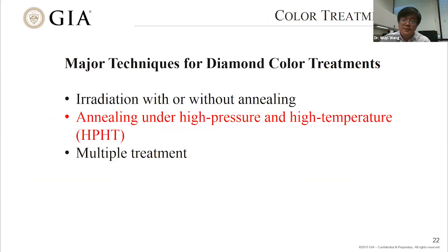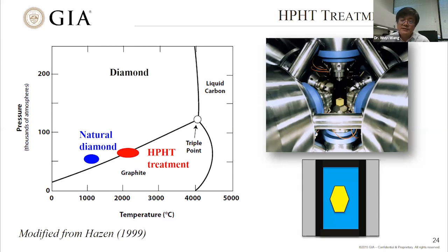For HPHT annealing, in this diagram I try to show the phase diagram of carbon. It shows the graphite stable region and the diamond stable region, by pressure and temperature. We know natural diamond is basically formed at about 1,000 to 1,200 degrees C, about 5 GPa. Most natural diamond formed at about this condition. For HPHT treatment, they maintain a similar pressure, about 5 to 6 GPa, but the temperature is increased much higher, to 2,000 degrees C or sometimes 2,200 degrees C, for a short period of time. At such a high temperature, the diamond mostly stays in the diamond stable region, or a little bit in the graphite stable region for a short period of time.